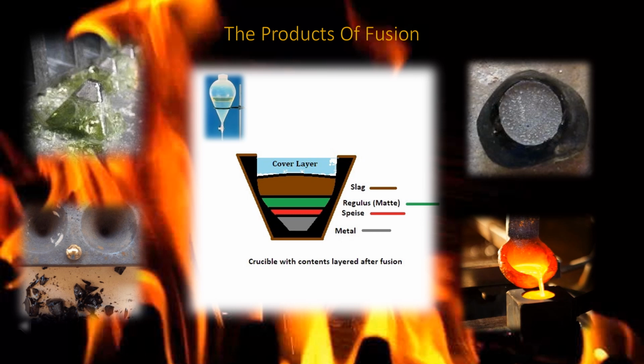Speiss is an unwanted layer. It is an artificial metallic arsenide or antimonide. Antimony speiss is rare. The more common is iron arsenide. It is a layer that is produced using the soda iron method of fusion when the contaminant is arsenic. It may also be a nickel or cobalt arsenide. When the slag is broken, the lead button will appear to have a hard, tough tin white coating on top of the button. If the arsenic level was low, the speiss may appear as a small little button on top of the lead bead. However, if the arsenic levels are high, this may coat the entire top of the bead. There will be some gold, silver, and if any, some platinum group metals lost in this layer.